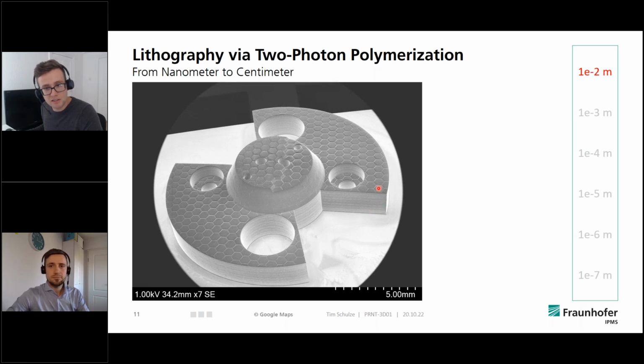So for instance, see this little structure. This has been printed by the objective in a steady position. And once this structure has been printed, it needs to move on to the next area and print there. And then those structures are printed together. And those can also lead to specific surface roughnesses above several microns. But in the end, it really depends on your application and what sort of roughness you need. So it's really a tricky question that, if it's really interesting for you, we can talk about afterwards.